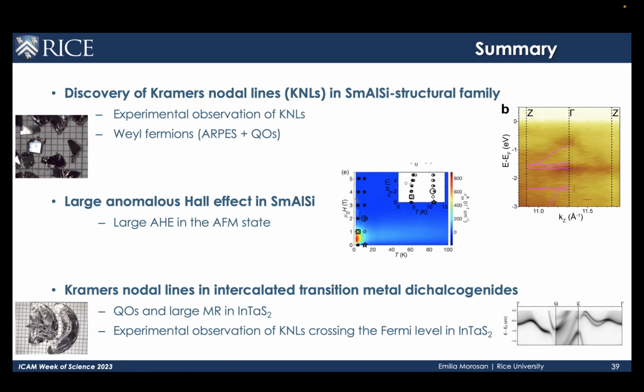Is there a reason samarium would not be 3+ here? Well, samarium is different than neodymium. Samarium is special in the sense that it has low-lying crystal field levels. Chemically it's the same bonding in the same crystalline environment, but rare earths are similar only to a degree; especially for light rare earths, they tend to be unique and not as similar as the heavy ones are. But if it's not 3+, you should see some anomaly in the lattice parameter. Is it there or not? Pretty much, to within error bars, it falls in line with the lanthanide contraction, but a small deviation from 3+ will not throw you off that.